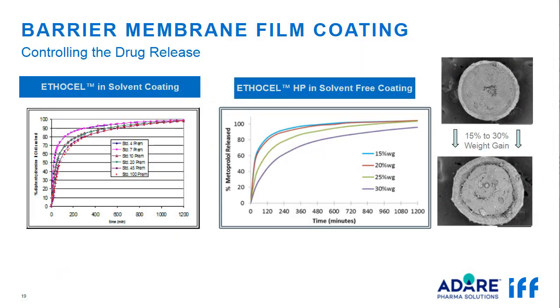The application of Ethocel in pharmaceuticals is mostly related to barrier membrane film coating and its lack of water solubility. Ethocel can be sprayed from organic solution, aqueous dispersion, or even used as dry powder for a solvent-free coating. Drug release can be modulated by polymer viscosity or coating weight gain, which is much easier. The graph on the left shows that by increasing the viscosity of polymer, we can slow down the release. And the graph on the right shows that drug release can be reduced by increasing the coating weight gain.